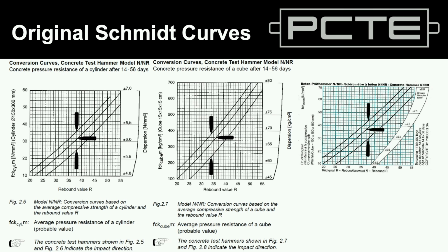There's some of the curves that you'll find in the manual, and the thing I want to highlight on all Schmidt hammer curves, some of them are made with cylinder samples like we use in Australia, and other curves are made with cube samples. If we go back to our compressive strength testing and we break exactly the same sample in a cube form versus a cylinder form, the cube form will break roughly 20% stronger than the cylinder, merely because of its geometry. The material is identical, the performance evaluation is identical, but the compressive strength required to break it is higher. So watch out for these samples.